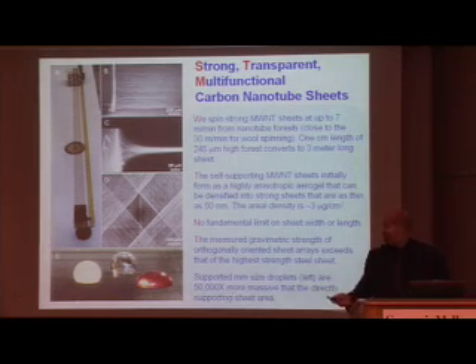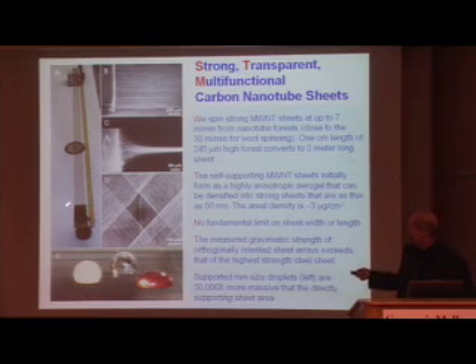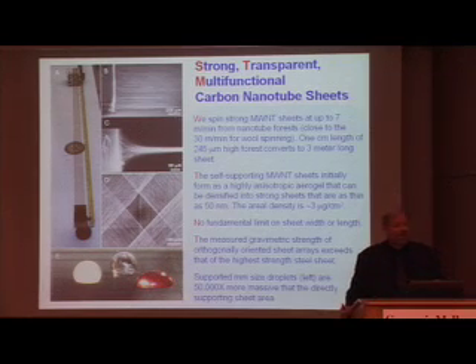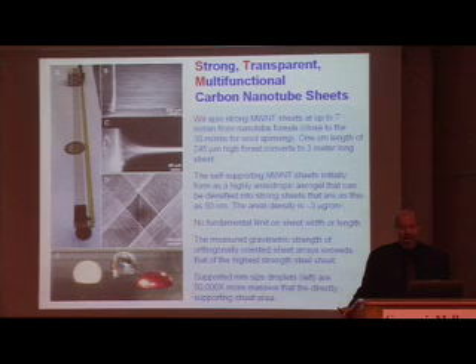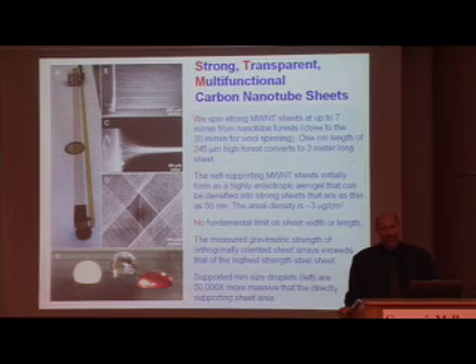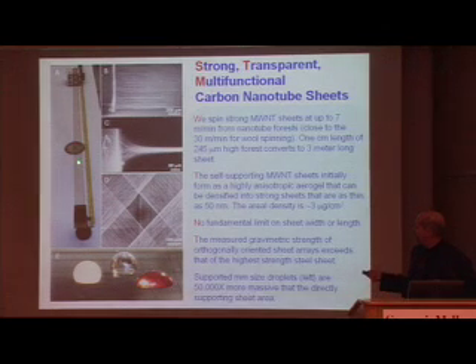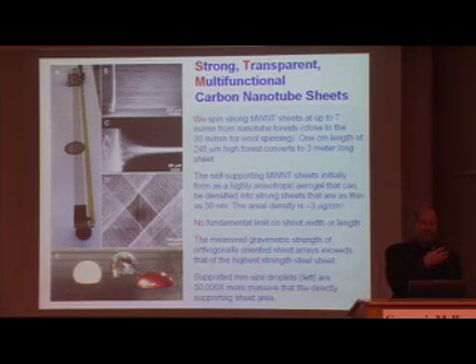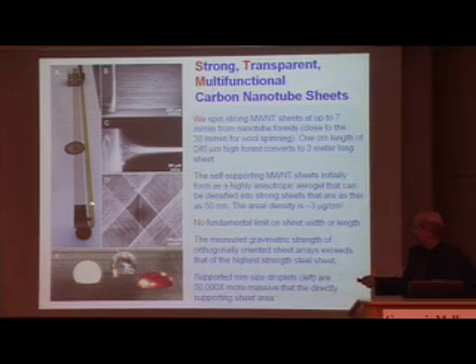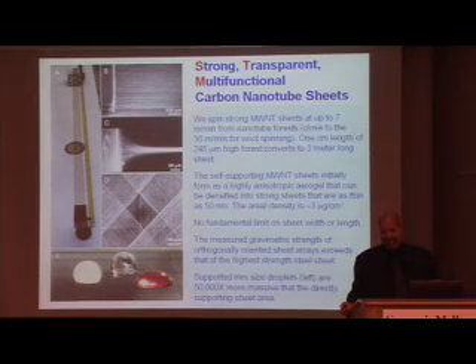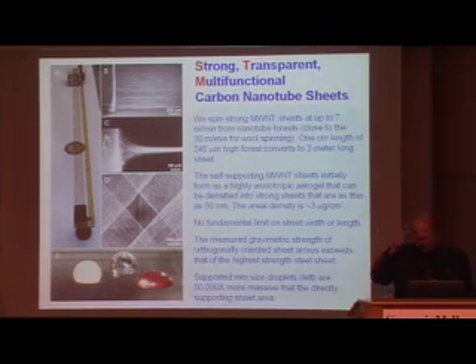But on a gravimetric basis, these sheets that we pull out of the forest, which is down here, have a strength which is higher than the Kapton and the Mylar, which is used for ultralight air vehicles, and stronger than the strongest steel plate. On a per weight basis, that's why if this sheet is densified by a process in which we expose the sheets to a liquid, allow the liquid to evaporate, the thickness of the sheet is only about 30 nanometers. And again, which is of order 3 orders of magnitude lower than the diameter of a human hair.